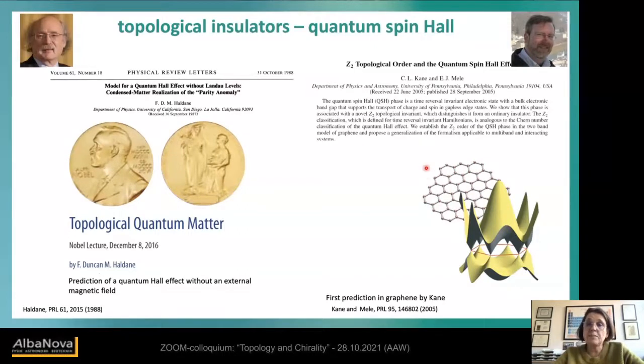Graphene, so if you need spin-orbit coupling, you need heavy elements. So graphene is maybe not the ideal material, but with this publication, immediately people recognized that this can go far beyond what the quantum Hall effect was. This was a complex system in a two-dimensional electron gas, where you did some measurements at very low temperature and ultra high fields, but it was not an area of research broadly. But here, the quantum spin Hall effect and the topological insulators have opened a huge field, also concerning materials.